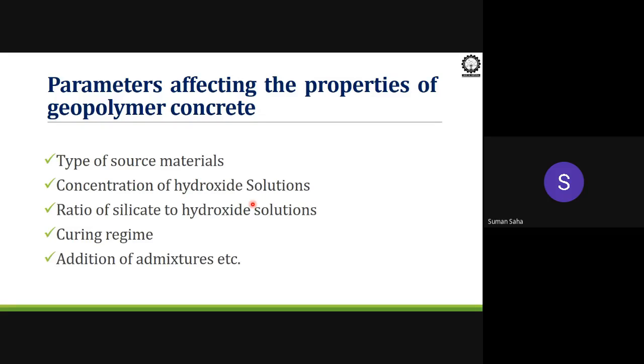And the curing regime is one of the added advantages, you can say. In OPC concrete, we need moist curing for 28 days, so it will give you the highest strength. But geopolymer concrete sometimes comes as alkali activated concrete also. There is a long debate, geopolymer concrete versus alkali activated concrete. I am not going into that debate, but again, this is also a very hot topic for research. What I want to mention about the curing regime is that without any moist curing, it can be kept at ambient temperature. In air curing, it can gain strength.